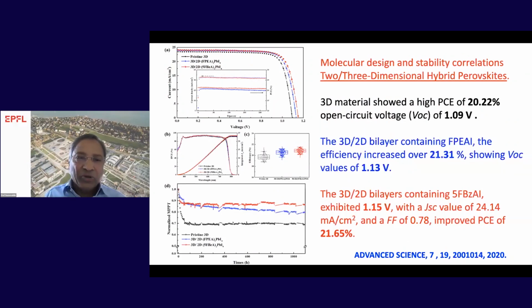So what does it give you? Here is the comparison between the photovoltaic data versus stability. The reference sample has a 20% efficiency with 1.09 volts. Now, by putting the fluorophenylethylamine on top of three-dimensional perovskite, the power conversion efficiency increased from 20 to 21%, and the VOC from 1.09 to 1.13, that's the blue line. Now, by putting the two-dimensional perovskite containing pentafluorobenzylamine on top of three-dimensional perovskite, you can see the power conversion efficiency from the reference sample 20 went up to 21.65. The VOC increased from 1.09 to 1.15, that's the red line.